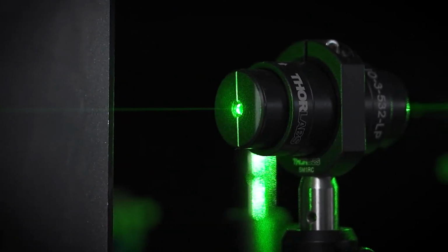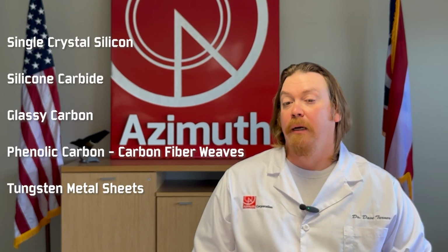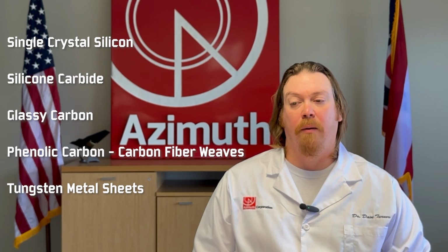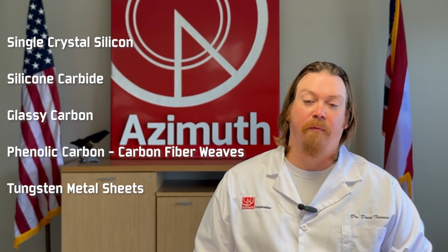Raman spectroscopy indicated that the coating applied had a definitive vibrational mode of the final metal oxide desired. This demonstrates that the coating is robust and thick enough to be identified via this spectroscopic technique and has some crystalline nature for the long-range vibrational modes of the crystal lattice. These Raman signatures were identified on all the substrates that were coated, including single crystal silicon, silicon carbide, glassy carbon, phenolic, carbon-carbon fiber weaves, and tungsten metal sheets.